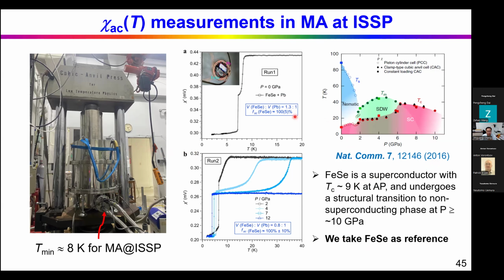So we first checked this single iron selenium. We put the iron selenium and lead in the coil, and measured at ambient pressure and at high pressures. The iron selenium will undergo a structural transition from the layered structure to a three-dimensional structure above 10 GPa, and above 10 GPa it is non-superconducting. Indeed, as you can see here, at low pressure we observe the transition from the iron selenium and also the lead. At 12 GPa, we only observe the transition from lead. The iron selenium becomes non-superconducting. So we can safely use iron selenium as a reference.